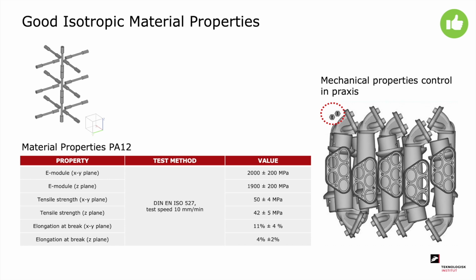Another advantage of the SLS technology is that we have really good isotropic material properties. That is, however we orient the part in X, Y, or Z direction, we get pretty much the same characteristics. All you need to be aware of, as you can see in the bottom of the table, is that you have a difference in the elongation at break, depending on if you build it in the XY plane or in the Z plane, which is the build direction.